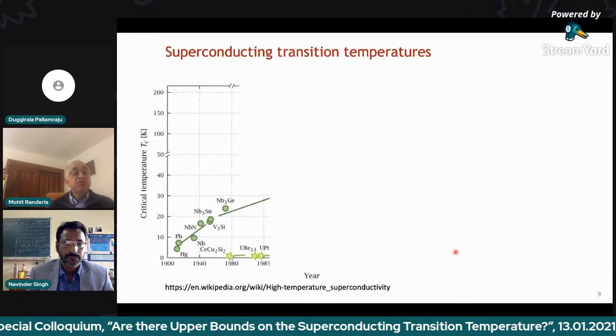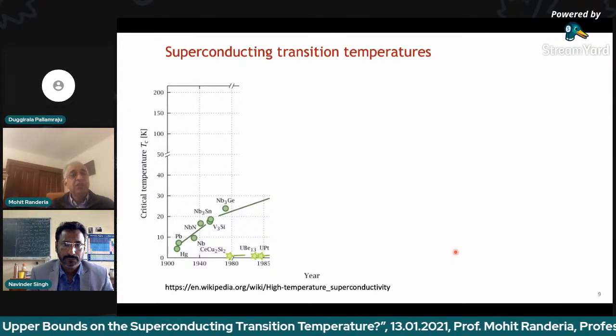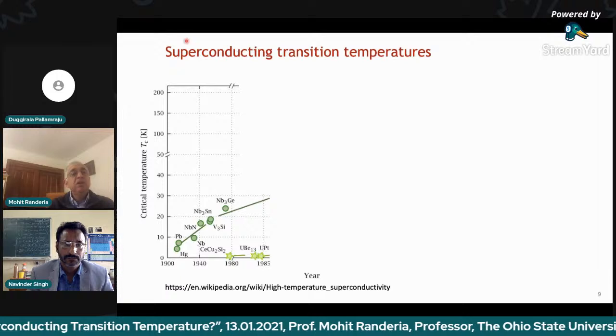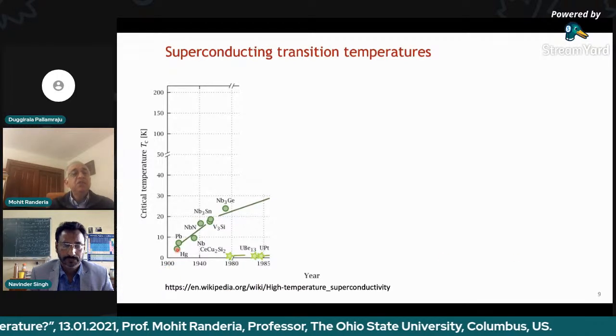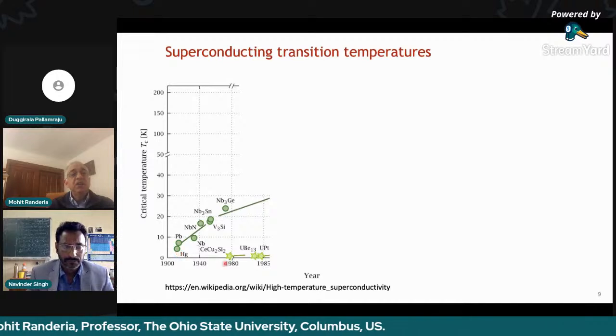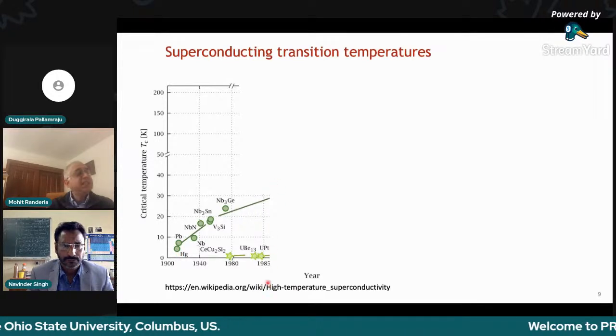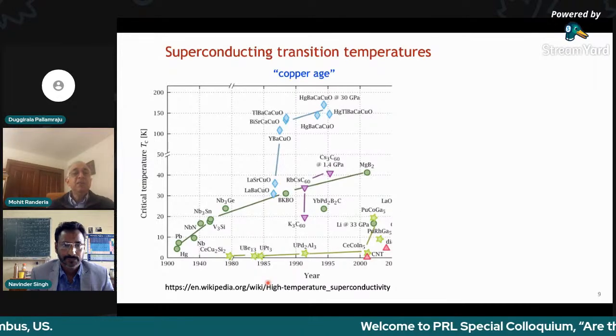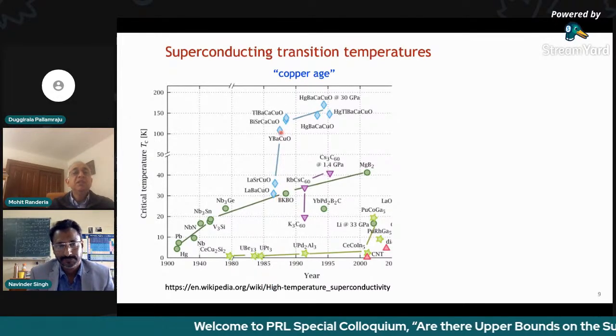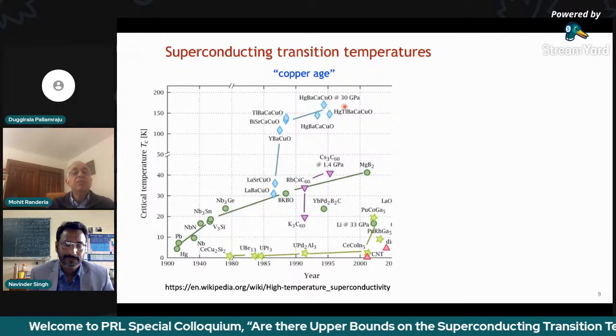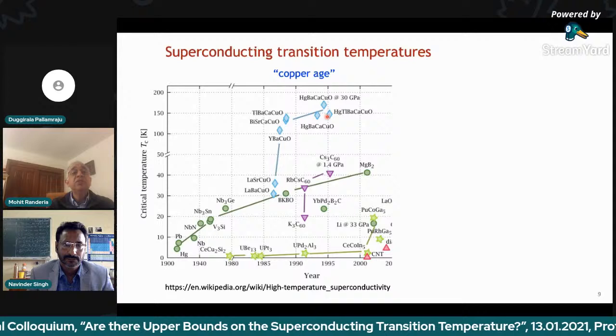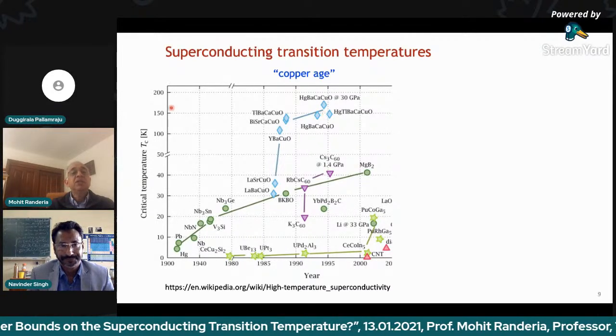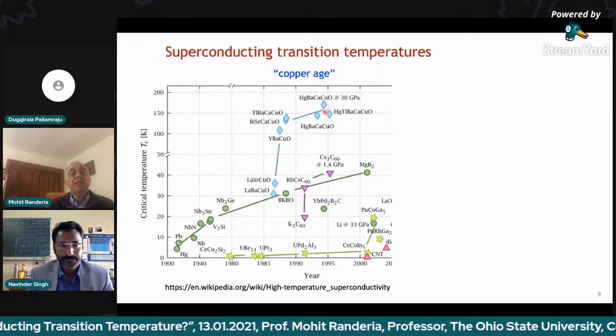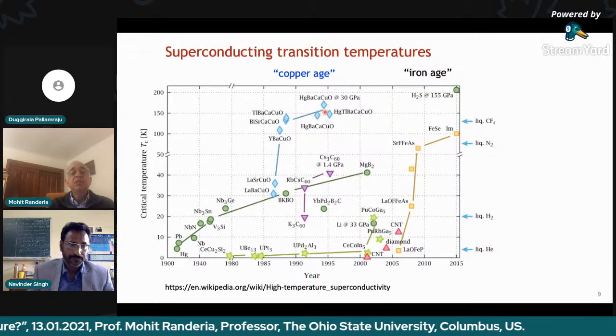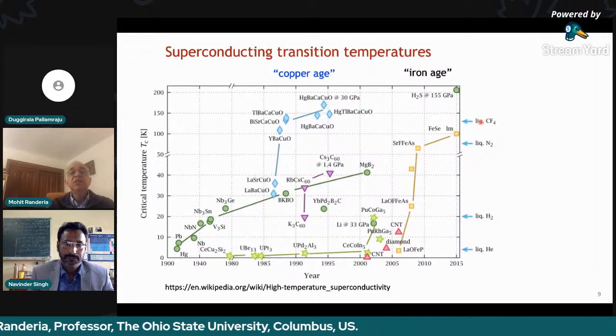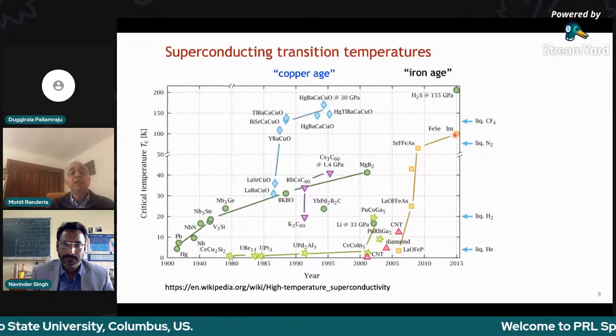Now let's look at superconducting transition temperatures, because that's the focus of the talk today. So here I'm showing you a plot of the transition temperature versus time. The first superconductor is mercury, and now this is where my PhD happens, 1987. So I stopped there, okay? And then comes the copper age of superconductivity, boom. These are the high temperature copper oxides whose transition temperatures are still actually the highest transition temperatures known at ambient pressure, close to about 150 or 160 Kelvin. Okay, and then comes the iron age of the iron-based superconductors, which also actually go up to about 100 Kelvin.